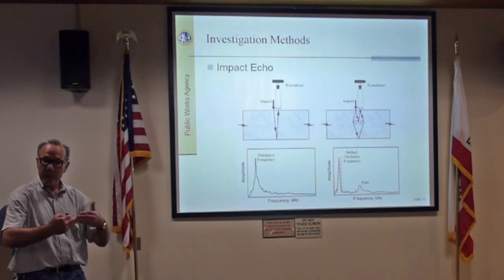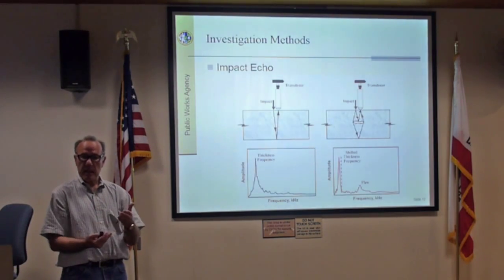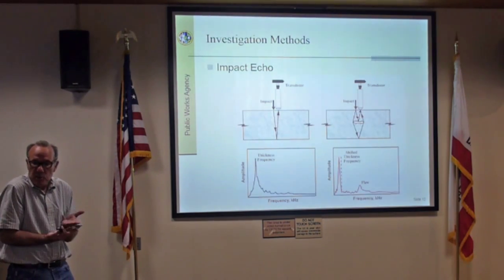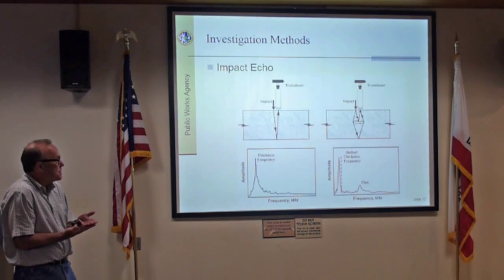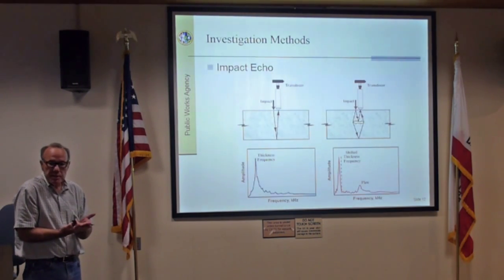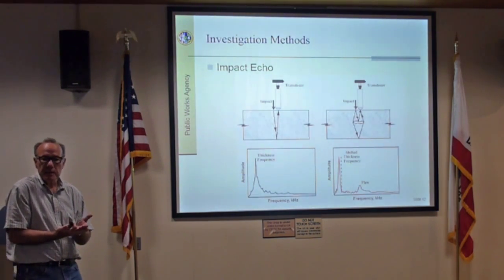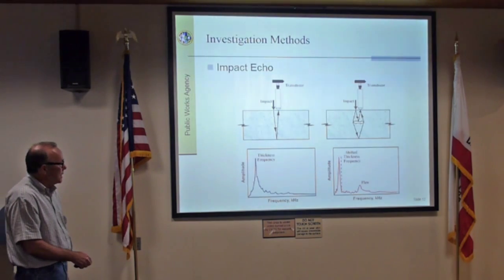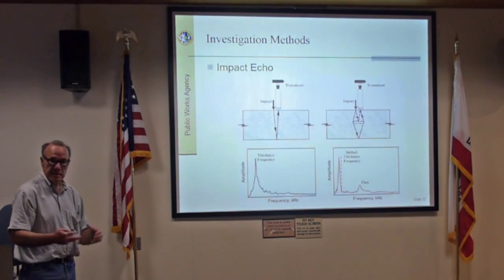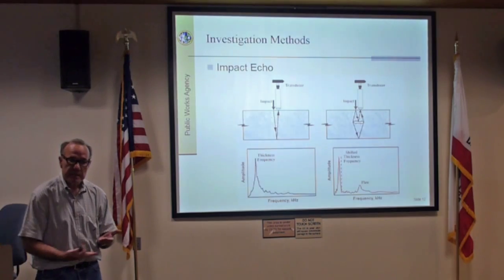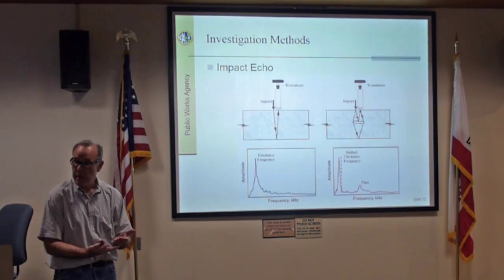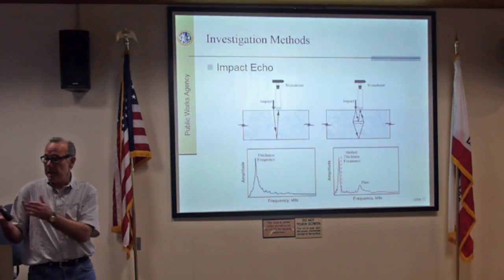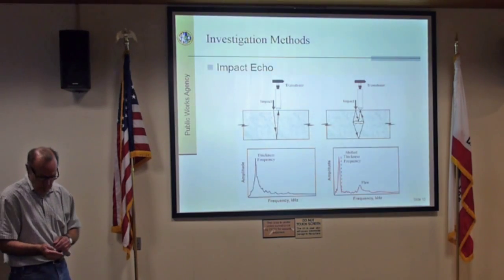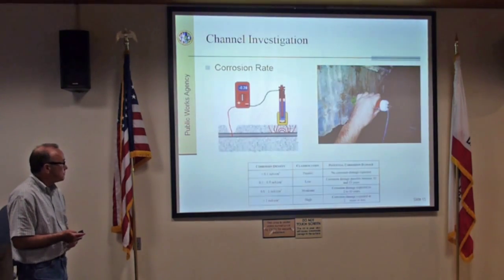So what we're doing is going near that starter wall joint. If that joint is very good and acting as a composite, well-consolidated concrete, we won't see a reflection. If we do the signal there and we get this type of signature, that tells us it's not well consolidated, which means it might be vulnerable for water to come in at that joint. So that makes it a higher risk in terms of your particular channel walls.